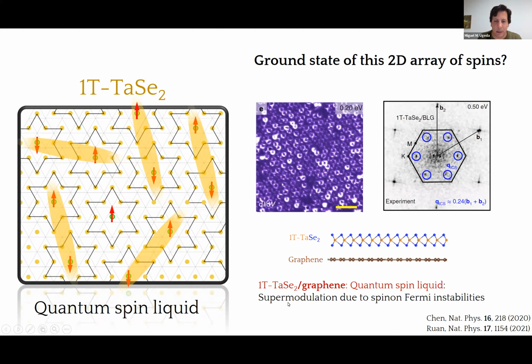The reason that supports this claim is that in this material, when it's grown on graphene, they observe a supermodulation that they ascribe to the existence of a spinon Fermi instability. A spinon is basically an excitation of this ground state. You can see it as an isolated spin that is able to diffuse in the quantum spin liquid, right? That diffusion has some signatures at the Fermi surface, which you see here. I'm not going to get into details, but in principle, this is the fingerprint of the quantum spin liquid phase.